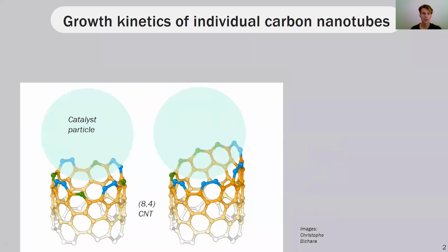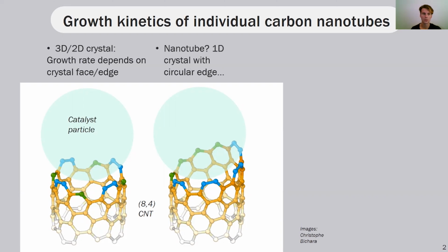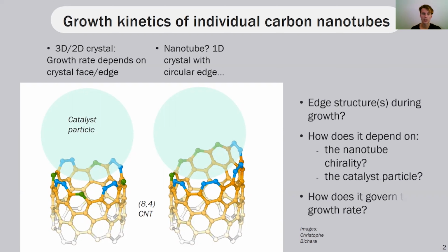The general motivation of this work is to shed light on the growth kinetics of individual carbon nanotubes, and from an applied point of view, it's important in order to develop chirality selective growth methods based on kinetic selectivity. From a fundamental point of view, it's well known that the growth rate of three and two dimensional crystals depends on their crystal edge or face. In a first approach, a carbon nanotube is nothing but a one dimensional crystal with a circular edge. This raises several questions: what is the edge structure during growth, or the possible edge structures? How does it depend on nanotube chirality or catalyst particle, and how does it govern the growth rate?